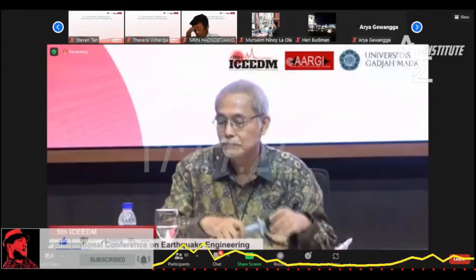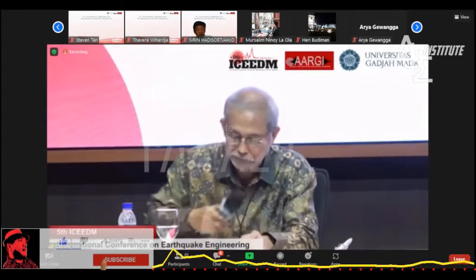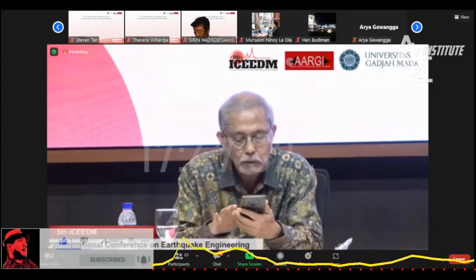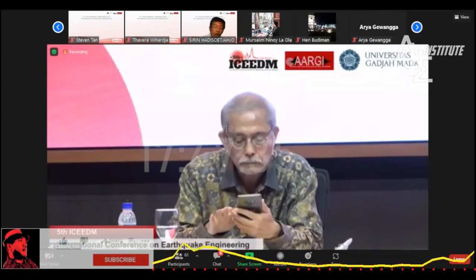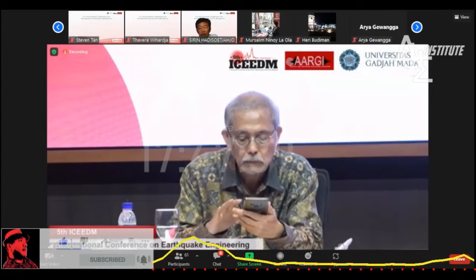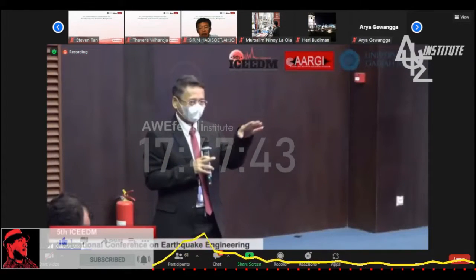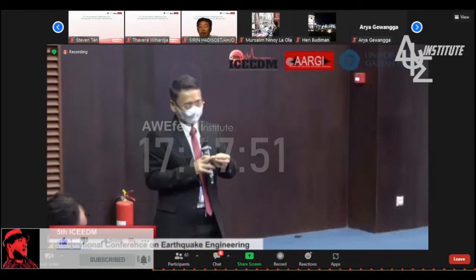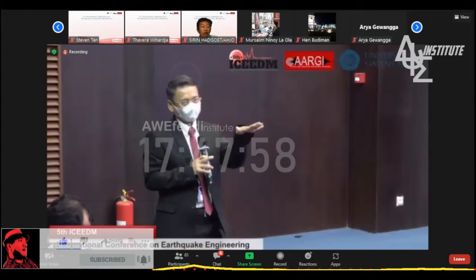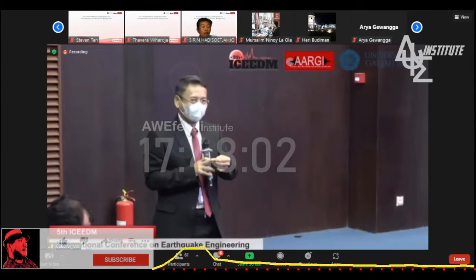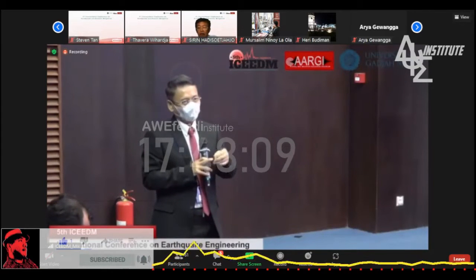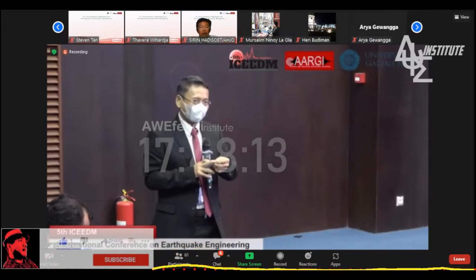Okay. May I add some comment? Yes. The importance of the requirement is to avoid, suppose we have the same strain, right? We hope that the strain will be compatible between the new concrete that we fill inside and the outer part of the spun pile. There will be a big difference in stresses. If the strain is the same but the modulus is highly different, then they will receive very different stress levels. The smaller modulus will receive the smaller stress, because modulus times strain gives the stress.